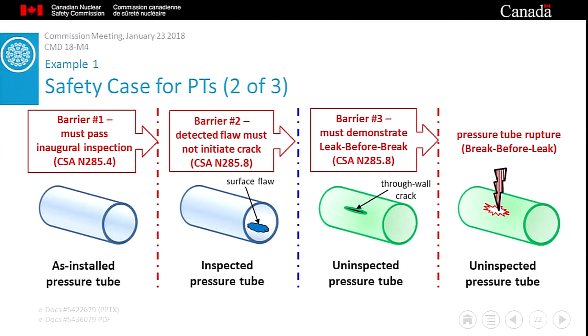In accordance with CSA standard N285.4, the licensee must periodically inspect a sample of their pressure tubes to look for flaws just like this. If the flaw meets CSA acceptance criteria, the pressure tube is considered unconditionally fit for service. On the other hand, if the flaw does not pass those criteria, the licensee must submit a fitness for service evaluation, basically a detailed assessment of the risk that the flaw could initiate delayed hydride cracking at some point. The assessment not only covers the present time, but a defined period into the future.